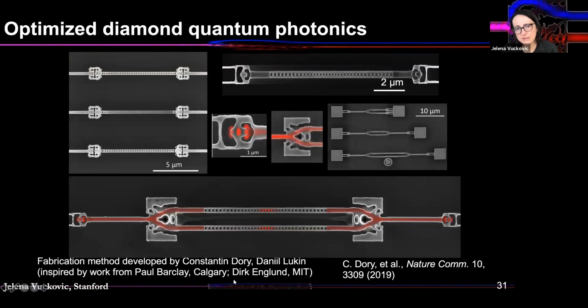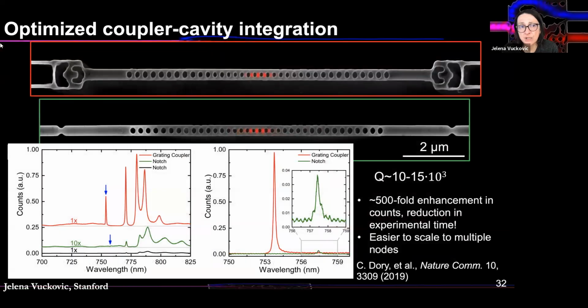And what is also very important is that these processes are fully compatible with our inverse design. So now with diamond, you see these inverse designed elements here that we optimize and also carve this way. And I should say that the method that we used was actually pioneered by Paul Barclay from University of Calgary, but it's used by us and also Dirk Englund at MIT and many other groups now. So it's really a beautiful method of three-dimensional bulk carving that is compatible with optimized structures and works really well, because optimized devices can lead to much higher efficiencies relative to traditional approaches, same as in silicon. I mean, this is just a comparison for a very simple coupler, but we've done other elements as well.